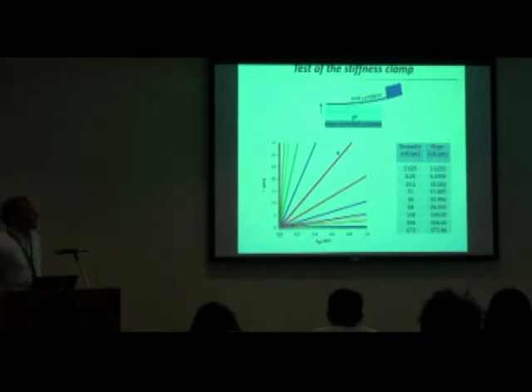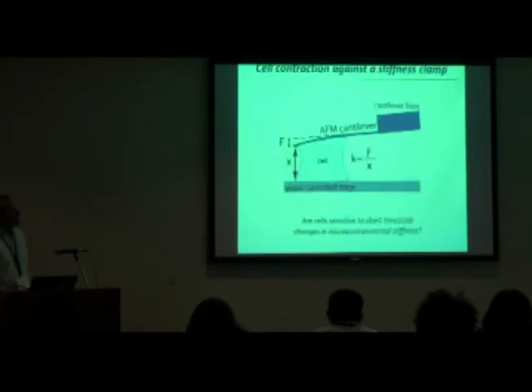So we demonstrated that with some control experiments, just using an expanding gel, using a feedback algorithm that adjusted the movement of the cantilever base. We could see that the slopes were different, and these different slopes are different apparent stiffnesses. So what about with a cell? What you can do now that you have an ability to change stiffness dynamically is you can ask, does a cell sense that rapid change in stiffness? If my clot is changing its stiffness rapidly, do I have some way of sensing that? Or is one platelet going to sense one stiffness, and only when it's done and another platelet comes in, can it sense that next stiffness? So we wanted to test that.